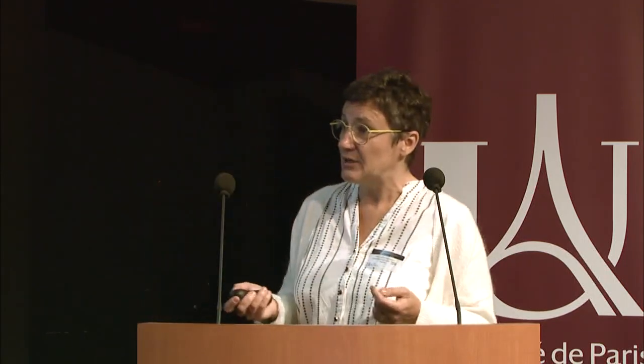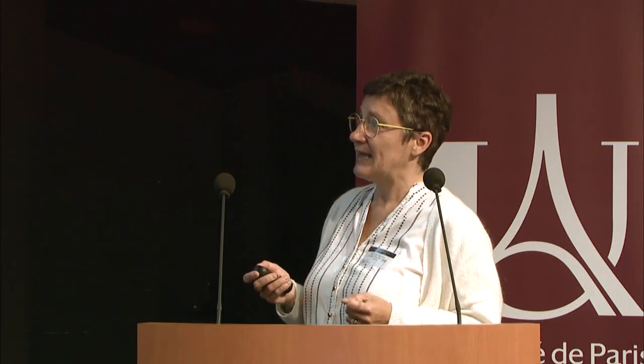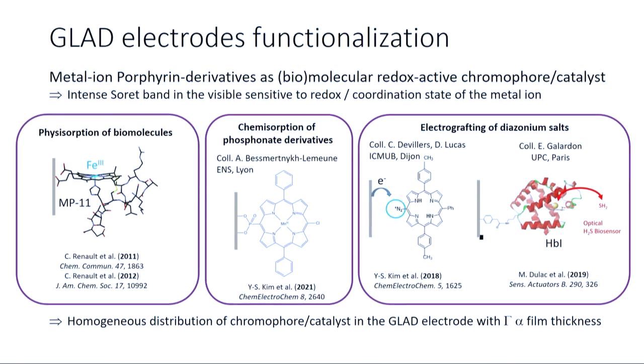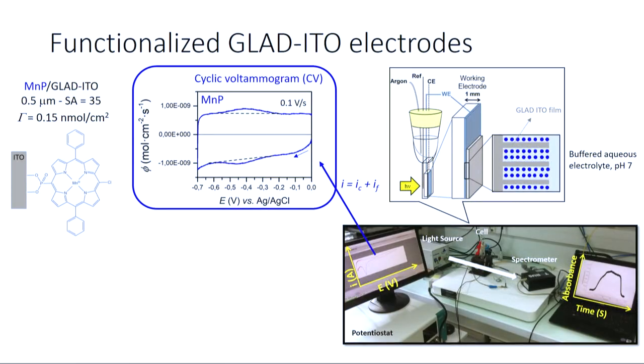But whatever the methodology used to functionalize the nanostructured electrode, what we demonstrated is that you have a very homogeneous distribution of the catalyst or the chromophore throughout the entire film thickness of the electrode, and so the surface coverage that you can reach is directly proportional to the film thickness of the electrode. So what happens next if we use this kind of redox-active chromophore and immobilize it in an indium tin oxide electrode? For that purpose, we use an electrode that has a film that is 500 nanometer thick. It has a surface enhancement of 35, and we get this kind of surface coverage for the manganese porphyrin.